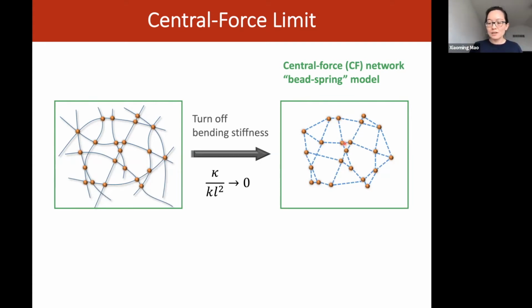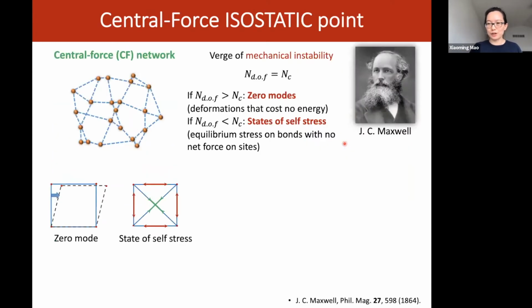Okay, so the mechanics in this simple limit has been studied for a long time and it really dates back to Maxwell. From Maxwell's work, we know that a mechanical network is at the verge of instability when the degrees of freedom and the constraints balance with one another. If we have too many degrees of freedom, we will have zero modes, which are ways to deform the network without changing any constraint, so it costs no elastic energy. And if we have too many constraints, we will have states of self-stress, which are ways to distribute stress on the network while leaving all of the components in force balance. So it is only when these two numbers are equal that the system is in a very special mechanical critical state, where you have just enough constraints for all of the degrees of freedom.